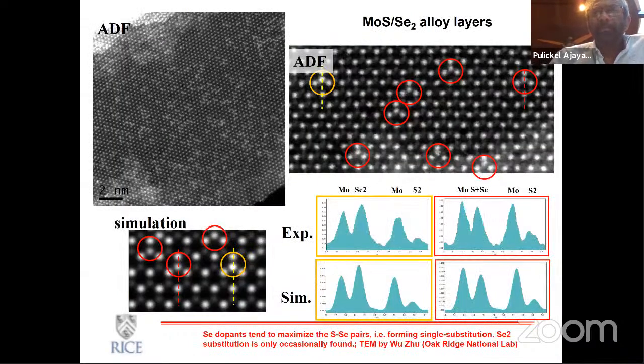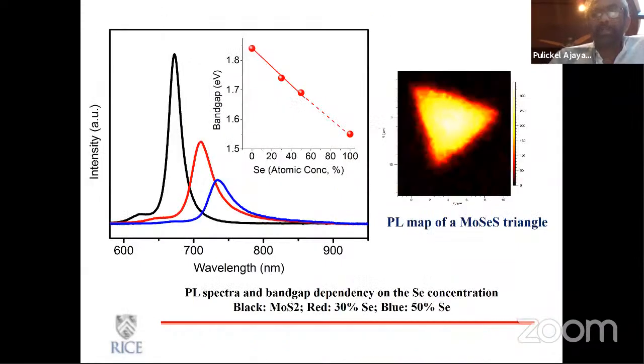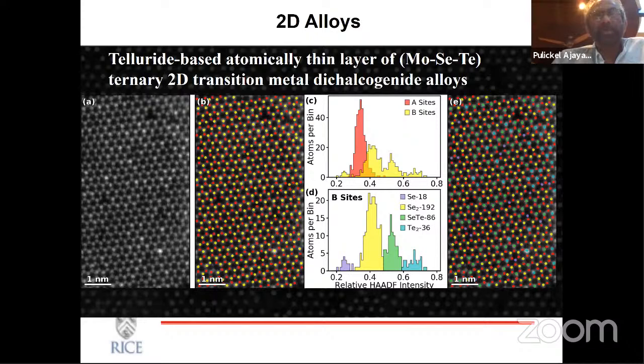So again, we did a lot of work in the last many years on understanding how exactly you can dope them and how they distribute in these two-dimensional layers. And unlike the segregated systems that you saw in the dichalcogenide systems, if you add elements which are at least compatible, like selenium in sulfides or different types of transition metals in these systems, they tend to distribute nicely and form alloys. And you can control the band gap within a certain range by changing the concentration of dopants. And again, these are some of the examples that we have worked on: moly selenium telluride, tungsten selenium telluride. And again, these are all really nice microscopy work based on some of these distributed alloys.